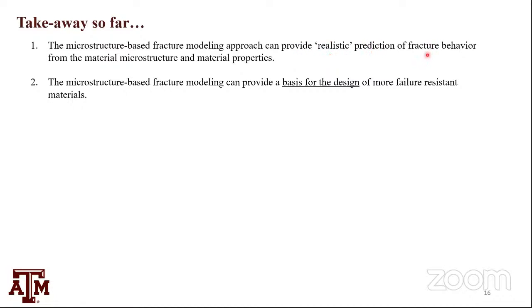So realistic prediction of fracture behavior from the material microstructure and material properties is not directly possible if you apply the widely popular, and actually not only widely popular, widely successful, engineering fracture mechanics based approaches, because you can't really get microstructure insight. These are not that popular, they're hard and not straightforward, but seem to have promise. These can also provide a basis for designing materials, as we saw in terms of grain boundaries, strength of material, and